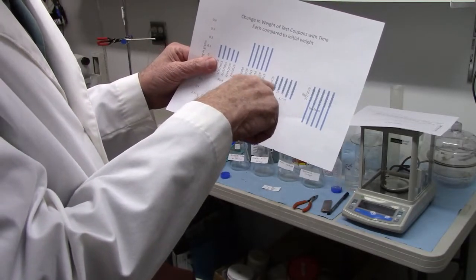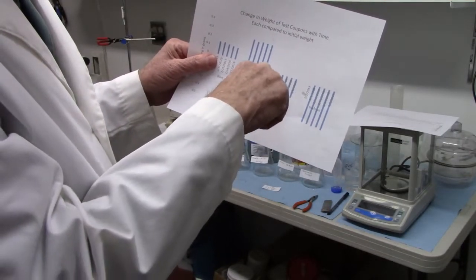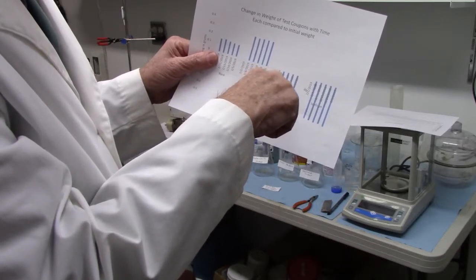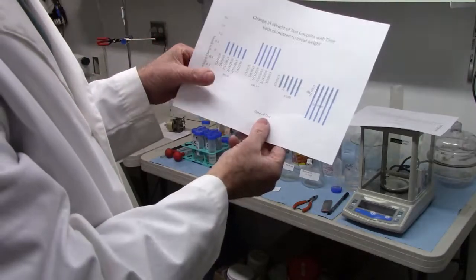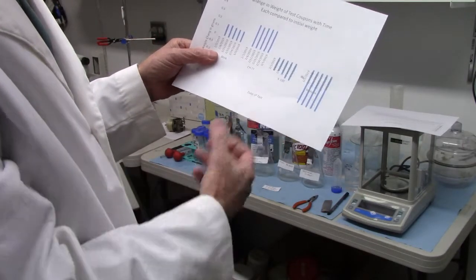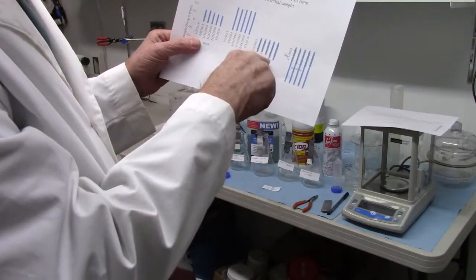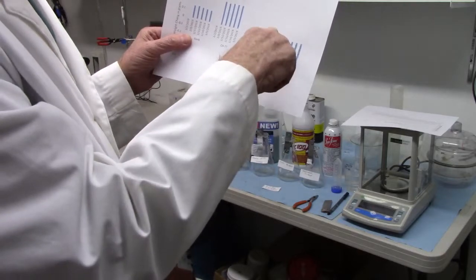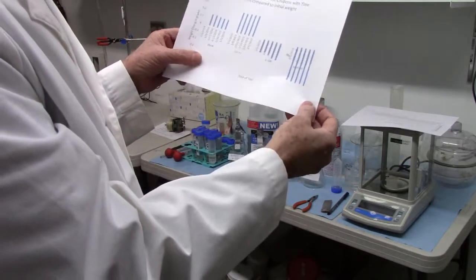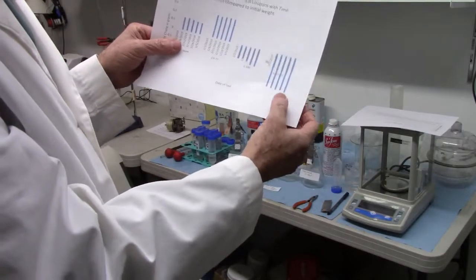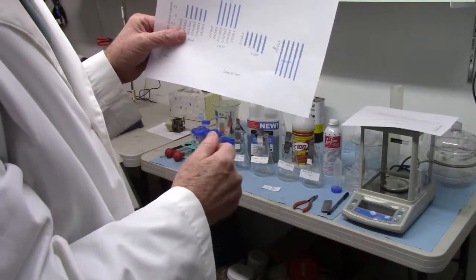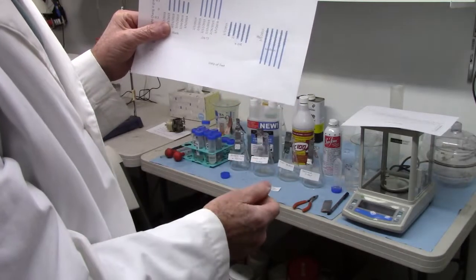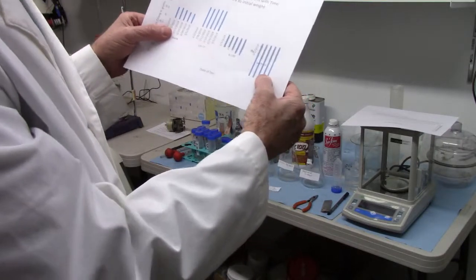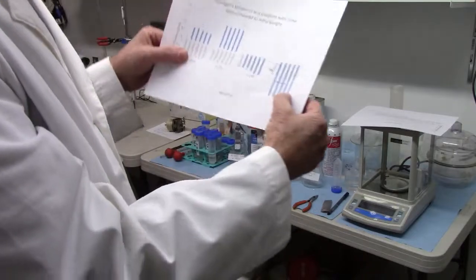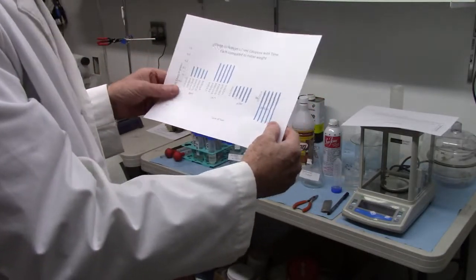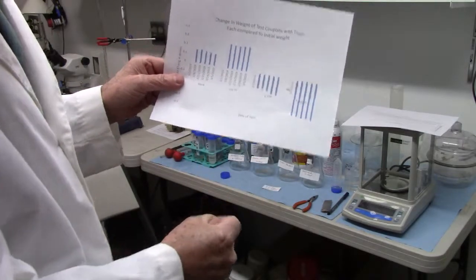And for the K100, the opposite happened. There was an immediate loss in weight with a progressive increase in loss. It started off losing roughly 200 milligrams and then went above 200 milligrams here. The Seafoam lost a lot immediately, over 400 milligrams per coupon. It lost immediately and progressively lost more as time progressed, and that was in there for about a month. So this is the result of the freshwater test.